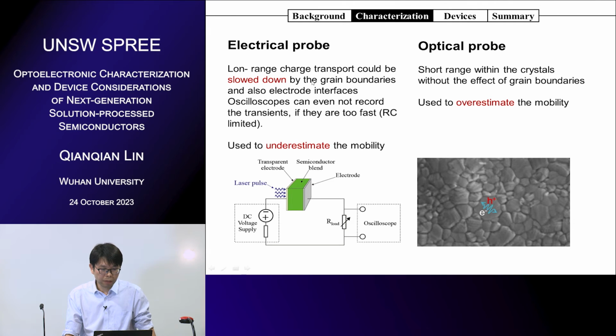And if I want to summarize these two classes of measurements, normally with electrical probes, like CELIV or TOF, we normally have underestimated mobility because you have the contacts, you have grain boundaries, the carriers have to go through the devices, and normally the values are slowed down.